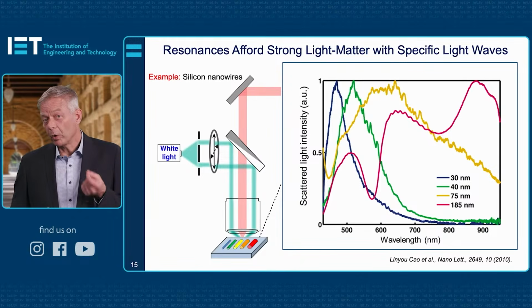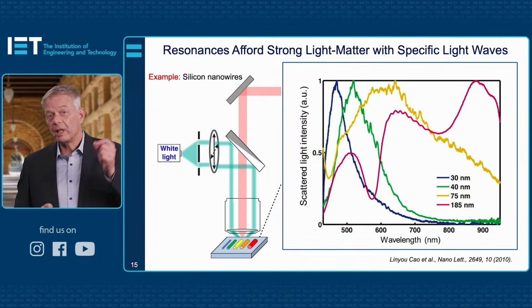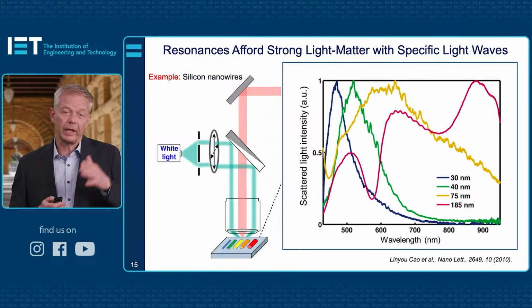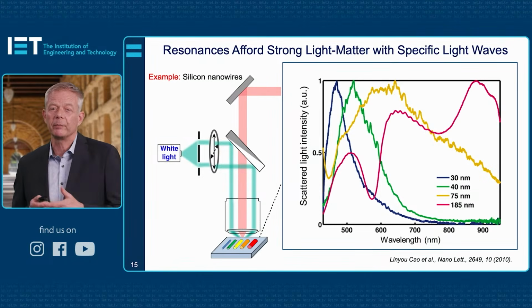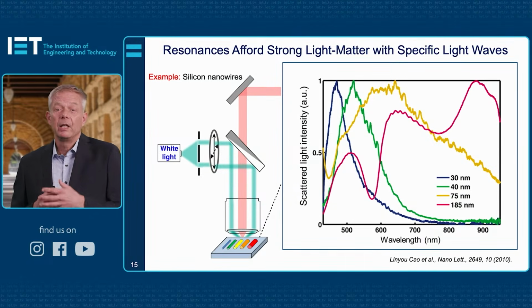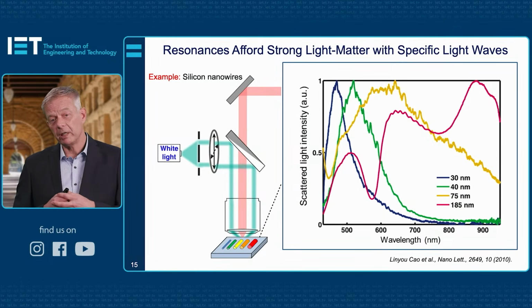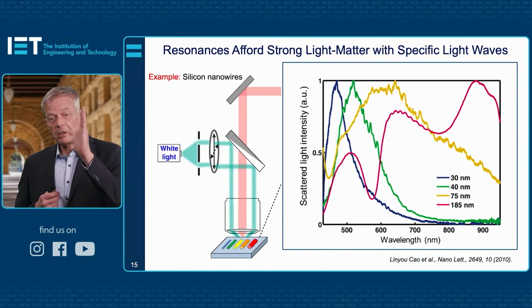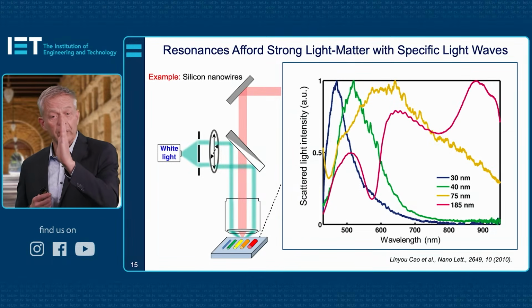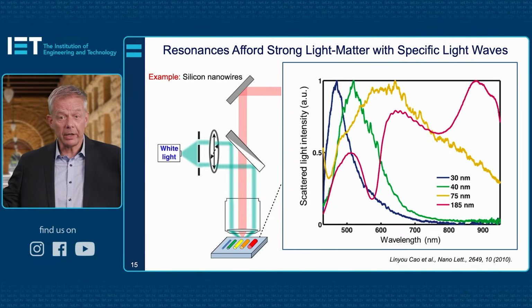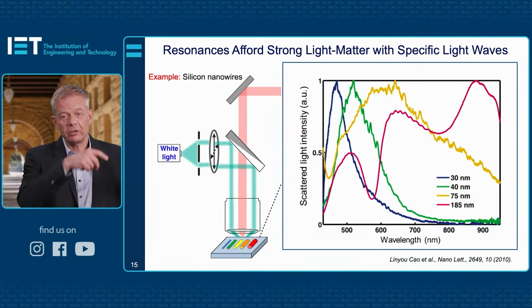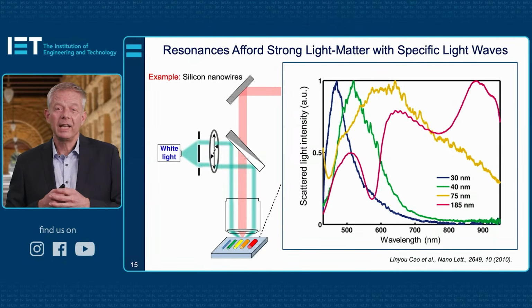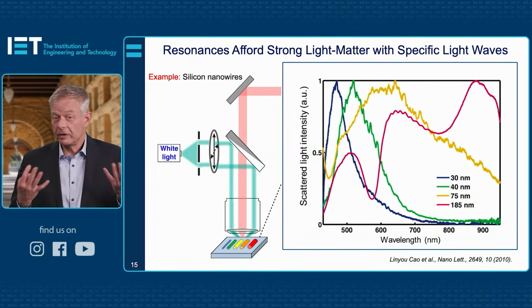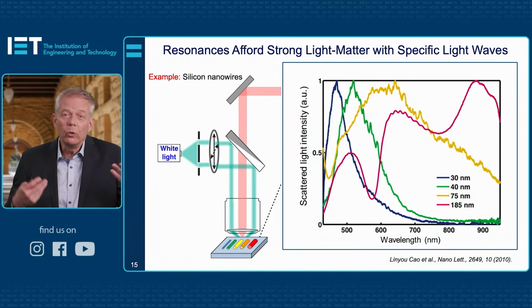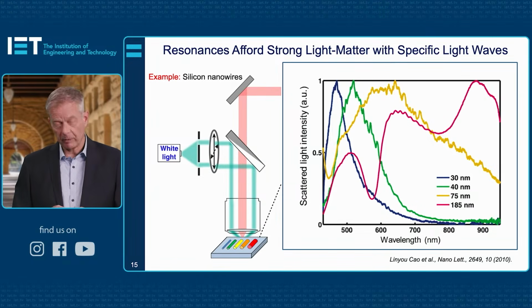Here you can see more quantitatively how the scattered light looks as a function of the wavelength, more or less from the blue part of the spectrum to the red to the infrared. And you can see, depending on the diameter of the particle that's listed here, that resonances may occur in the blue, the green, the red, or even bigger wires have multiple resonances, such as in the 185 nanometer wire, where resonances occur because we can fit 1, 2, or 3 wavelengths around the circumference.